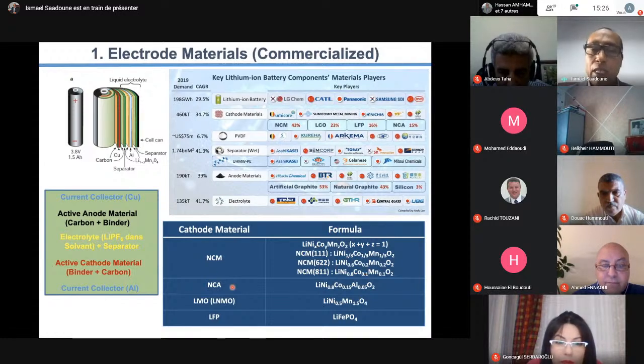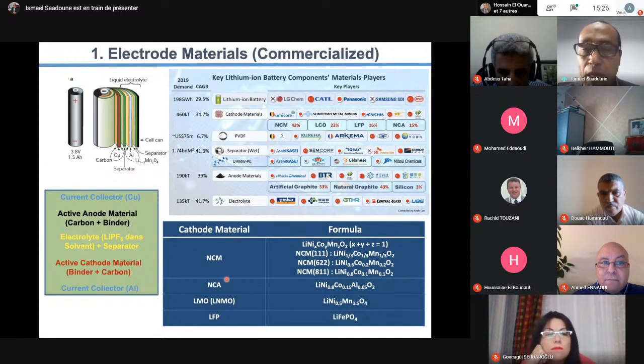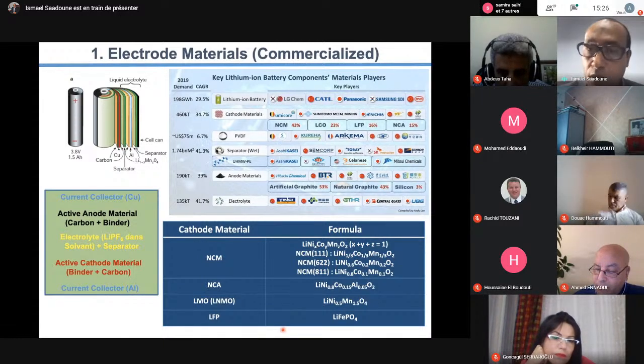The second example is NCA, which is used by Panasonic and Sony, for example. This is nickel, cobalt, aluminum. LMO or LNMO is a spinel made from lithium, nickel, manganese - it's a spinel cathode material. And LFP is lithium iron phosphate. This is the technology used in commercialized batteries.